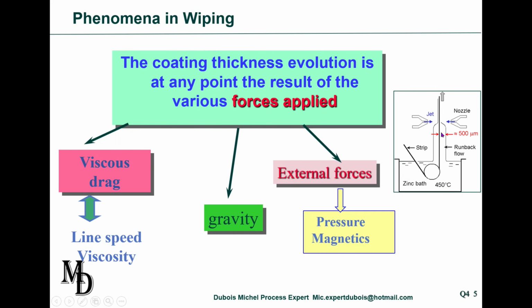The strip is moving out of the pot here, and so you entrain by viscosity force a certain amount of liquid, and you have to apply some external forces on that layer in such a way that the excess goes back to the pot. So this is only a force balance, and this can totally be solved by the Navier-Stokes equation, but we immediately see the main parameters. On one side, of course, line speed and viscosity will have a major effect. And the external force, which could be, for example, magnetic force or impact pressure, adjusts the final thickness. Magnetic has been investigated by different research labs, but it does not work well. That's why today everybody is using air nozzles and wiping nozzles.